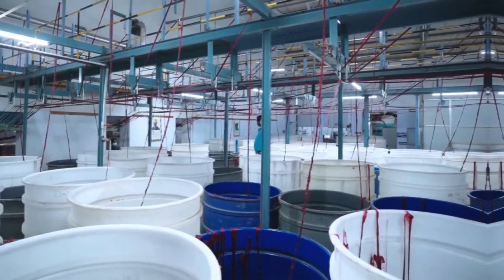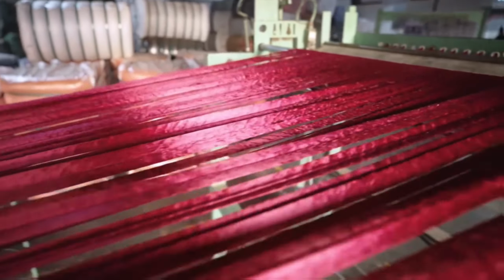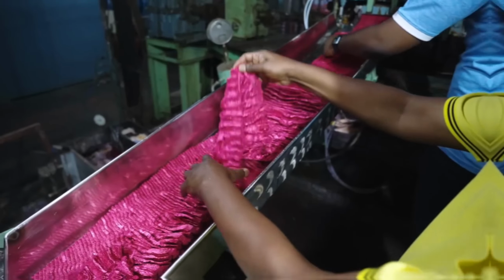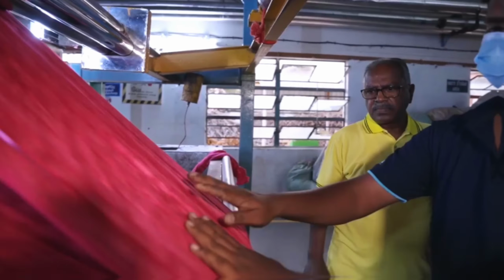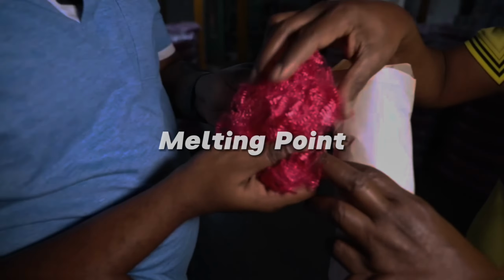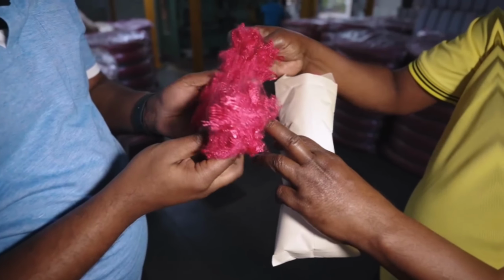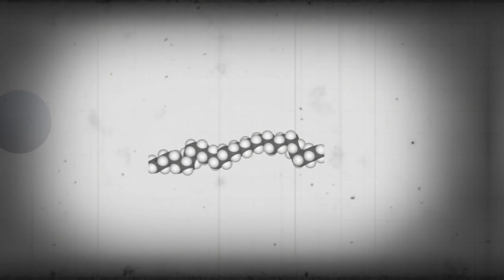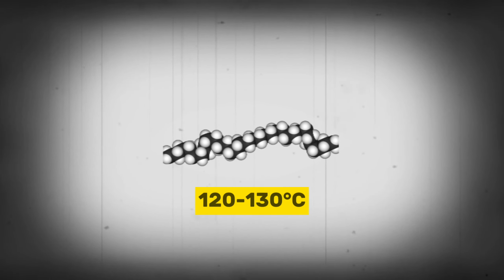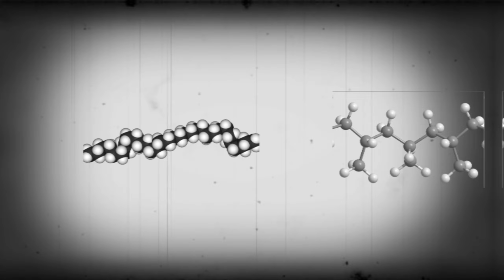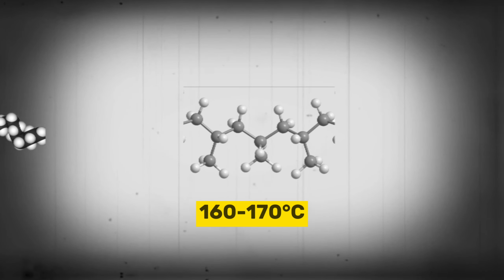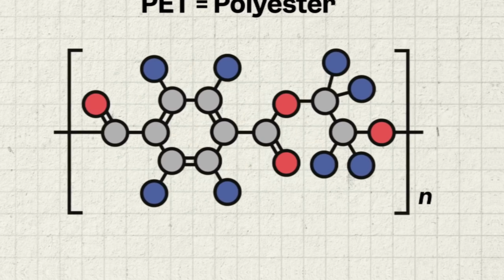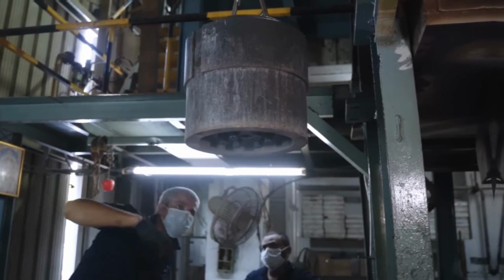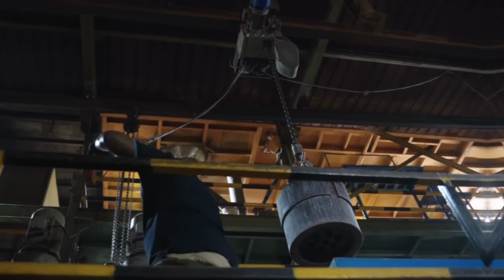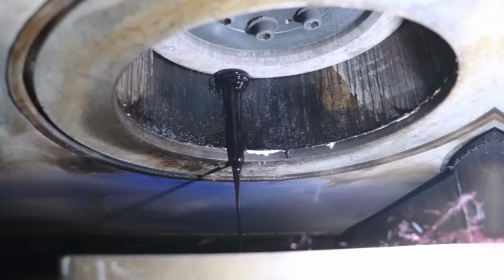Melting and extrusion are the next stages in plastic recycling, transforming collected plastic waste into reusable raw materials. The process begins by heating the plastic to a precise melting point in a specially designed extruder. The required temperature varies depending on the plastic type. For example, polyethylene melts at around 120 to 130 degrees Celsius, while polypropylene requires 160 to 170 degrees Celsius. Thermoplastics are well suited to this process since they can be melted and resolidified multiple times without significant degradation.